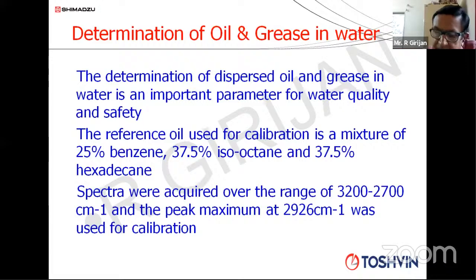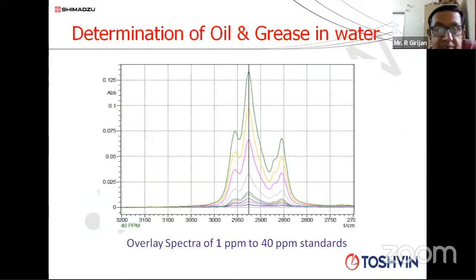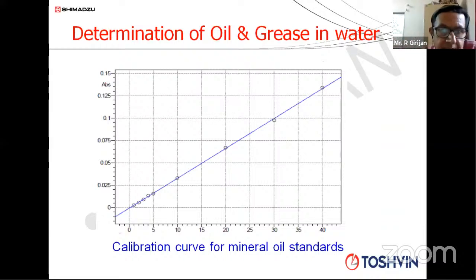And you can see a calibration, and we have prepared different standard materials right from 1 ppm to 40 ppm. For all the standards, we are measuring the absorbance at 2,926 inverse centimeter, and we are going to create a multi-point calibration curve. After this, we can measure the actual sample and find out what the oil and grease content in water is. It's an official method, and we have actually optimized this method in our lab.